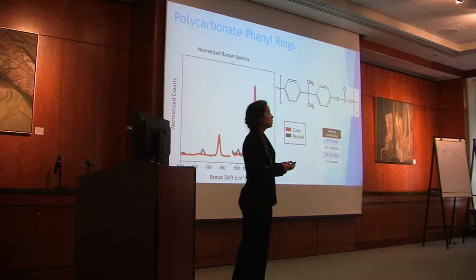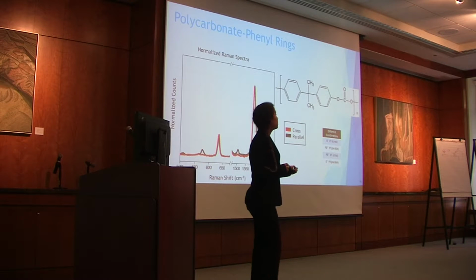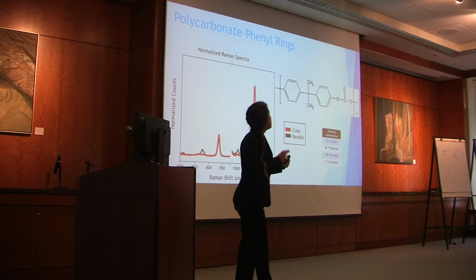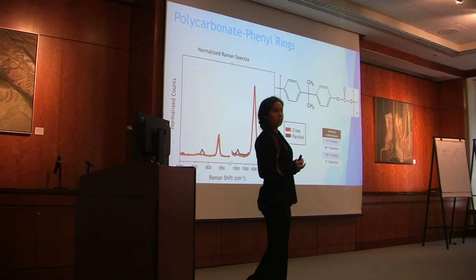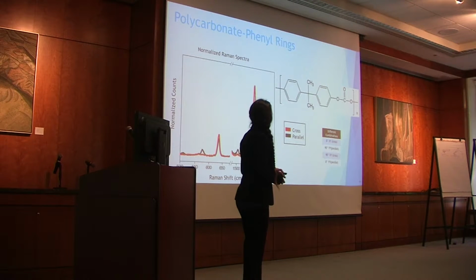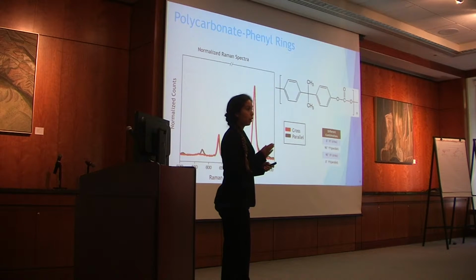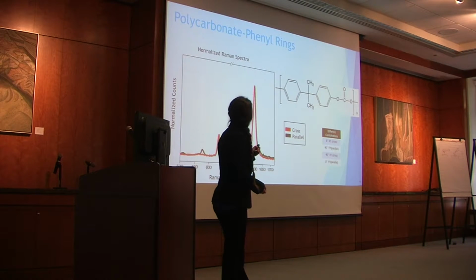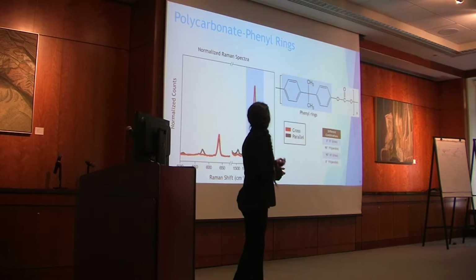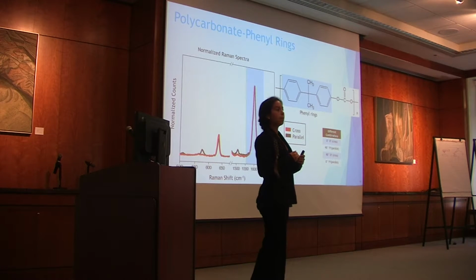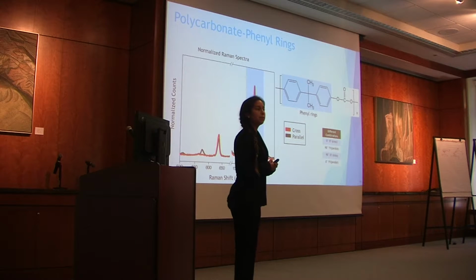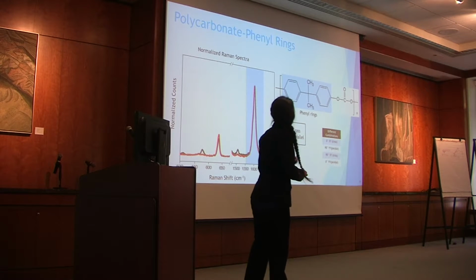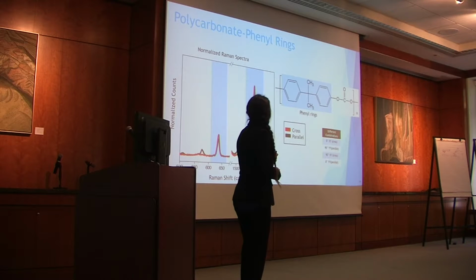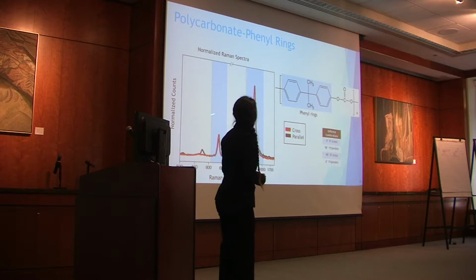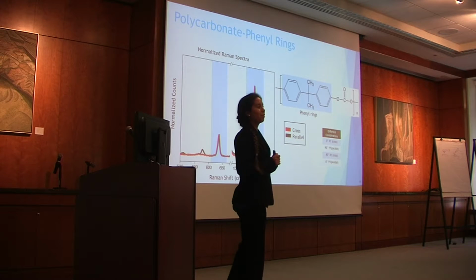When doing this, I will go back to the idea of polarized Raman spectroscopy. I looked at different combinations. Cross and parallel refers to the way that the incident light is changing. This is a graph of the spectra looking at the different cross and parallel polarized Raman. To start it off, we normalized the graphs to a phenyl ring so that we could better compare the different results. The reason that we normalized to a phenyl ring was because it's in the backbone and it's not expected to be affected by the parallel polarized Raman, so it shouldn't change in theory. We were reassured that it did not change when another peak that is associated with the phenyl ring auto-normalized. So this is great news.